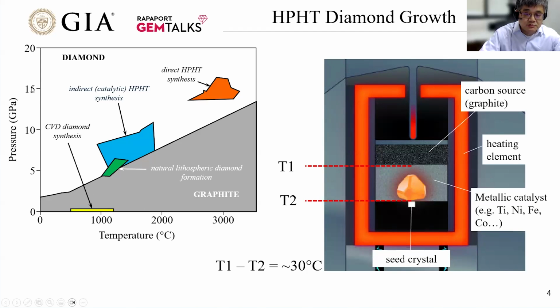But when the pressure goes up and the temperature goes up in this area, the carbon will stay as diamond. Diamond will be a stable phase at these pressure and temperature conditions. Natural diamond, this is gem quality natural diamonds, most of them are formed at about 5 GPa and 1200 degrees C. That's where the natural diamond formed in the Earth's mantle.